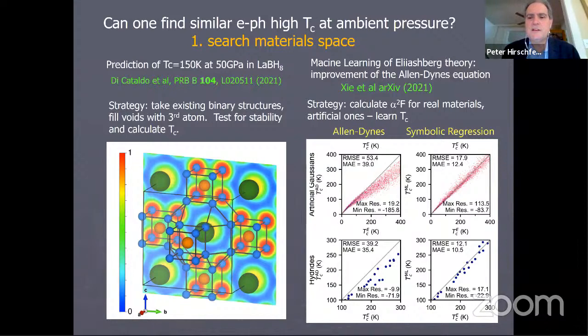Another thing you can do is to try to use machine learning to analyze the properties of many, many materials. Or if you're theorists, then many, many artificially created Eliashberg functions. This is something that we did in my group and found a new analog of the famous Allen-Dynes equation for TC, which depends on various moments of the alpha squared F function. Specialists know what I'm talking about. Others probably will not, but it doesn't matter. I just want to show you this is the kind of thing that people are looking at right now. And we found an equation which does a much better job for the critical temperature of the high temperature hydrides after being trained on the low temperature superconductors.